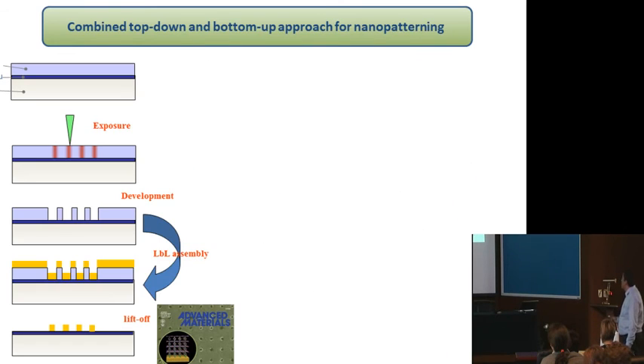So the extension of the formation of films is to obtain patterns. For this, we combine this layer-by-layer assembly with e-beam lithography. Okay. So for that, we deposit a conventional PMMA, polymethyl methacrylate, resist on gold. Okay. And on this resist, we write patterns using a focused electron beam. In fact, you modify the solubility of the resist. And then using an appropriate solvent, you can remove the irradiated part of the resist. Like this, we have these patterns. And using this pattern, you can again realize the layer-by-layer assembly. Okay. So in fact, here we have sulfur, of course, the anchoring layer. So using another solvent, you have this lift-off step, and that way we can remove the resist, obtaining patterns of these different materials.